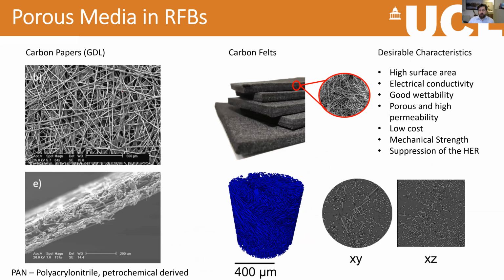So one of the key aspects of flow batteries, because we have this flow characteristic that we need to think about, and particularly the mass transport of the flow, is actually the type of porous media that we use in the electrodes. So normally flow batteries will use some form of 3D carbon structure, carbon fibrous structure, and these can be in the form of thin papers. And these are just basically taken straight from the fuel cell industry, something called a gas diffusion layer. Or you can use these more sort of thick 3D carbon felts, which are made from weaving a polymer and then carbonizing that polymer to give essentially graphite, so that it's electrically conductive. And those polymers are often PAN, polyacrylonitrile, which is a petrochemical derived polymer. The types of characteristics you want in these electrodes are obviously a high surface area, so you've got lots of sites for reactions. Good electrical conductivity, so you don't have these ohmic potential losses.